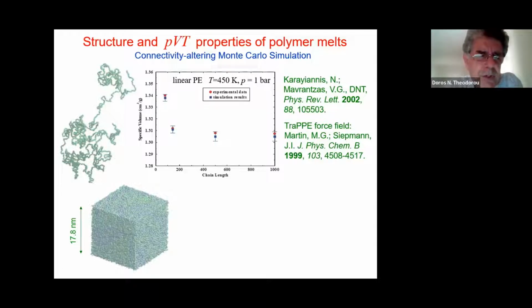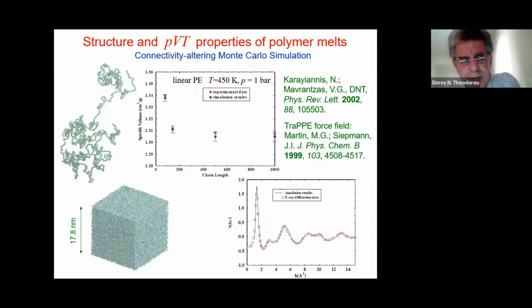And also we can accumulate pair distribution functions from the equilibrated simulations, and by Fourier transformation we can get static structure factors, the X-ray diffraction pattern. So here you see the X-ray diffraction pattern as a function of the wave vector for polyethylene again in the melt state. There is a first peak which is intermolecular in origin. It reflects intermolecular correlations between the carbons in the system. It's the amorphous halo. And then there are other peaks which reflect the intramolecular bonded geometry of the chains. Both are predicted very well in comparison to experiment. So we can equilibrate long-chain polymer melts.